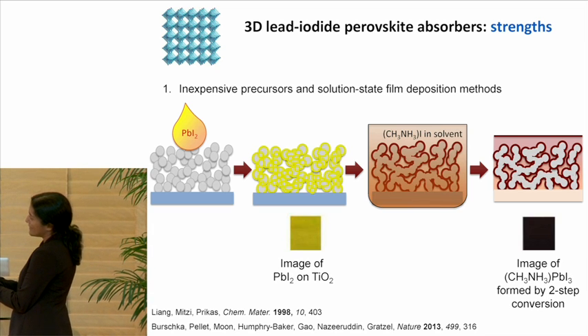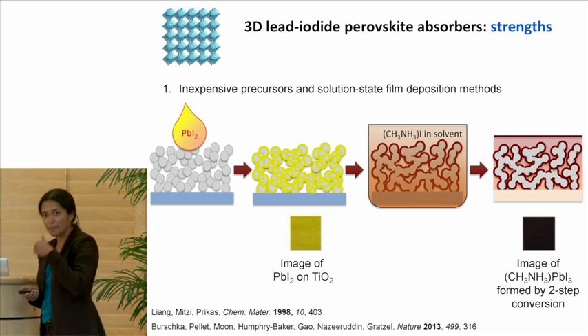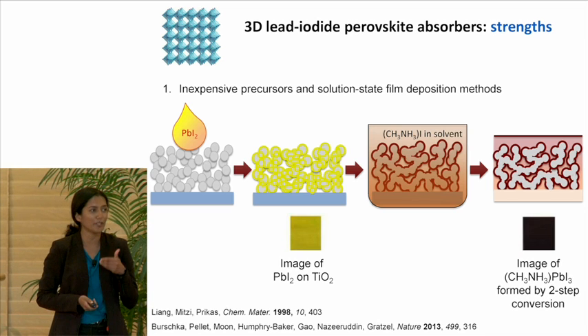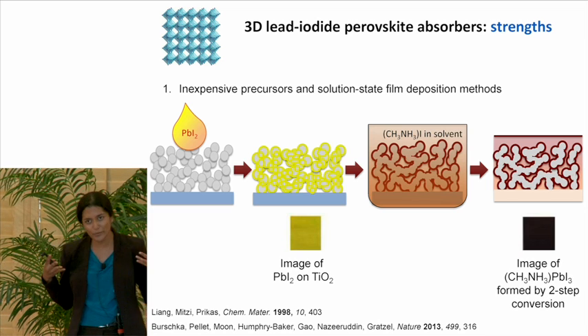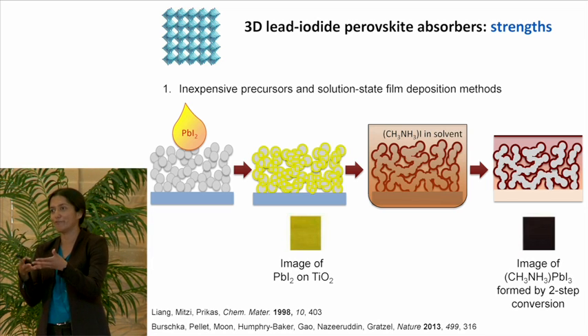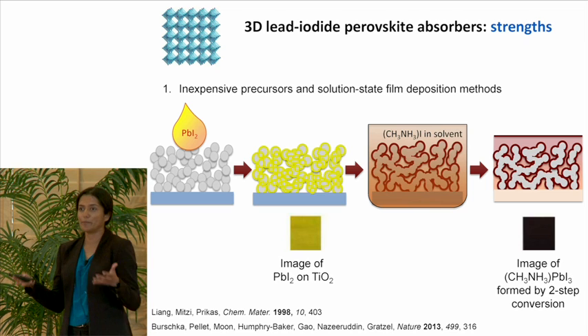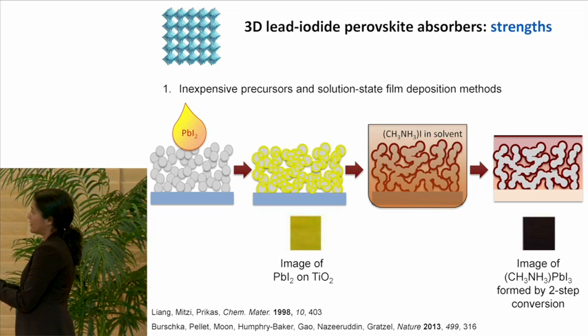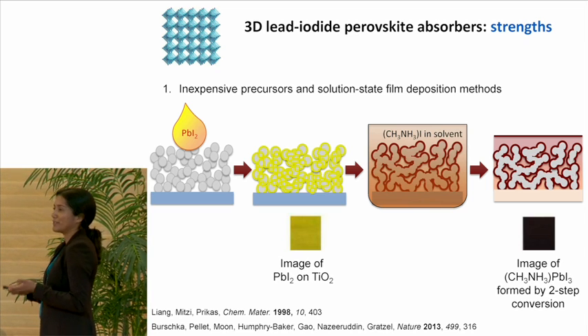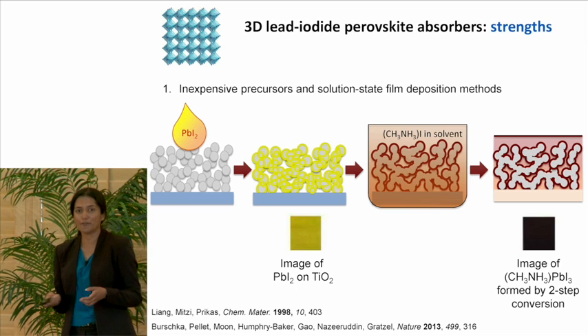We can then simply take this film and immerse it into a solution containing methylammonium iodide, and the methylammonium iodide will work its way in through the lead iodide film and convert that film into the perovskite. So our yellow film is turned black, and we are left with this beautiful uniform film of the perovskite.